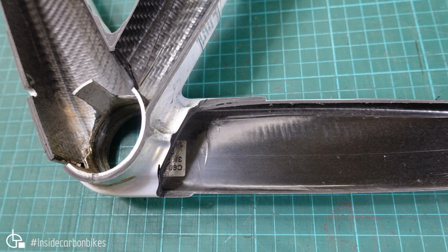And here we have the chainstay to bottom bracket junction, and if you recall, there was a void in the other one in exactly that same spot there, so they're consistent. And I did say on the previous one that it's relatively minor because it's so far from the edge, and there's significant bond area there, so it's highly unlikely it's going to cause any problems. The rest of it's all pretty good, looks pretty similar to the other one, same sort of little sticker, a little bit further in the joint.